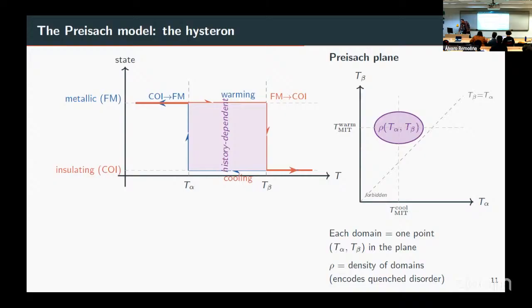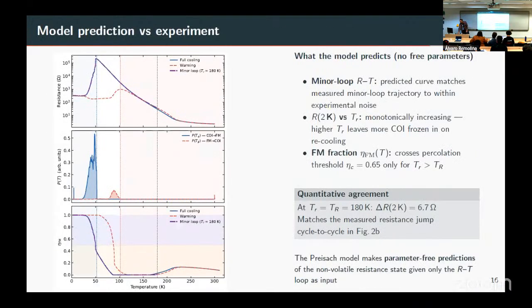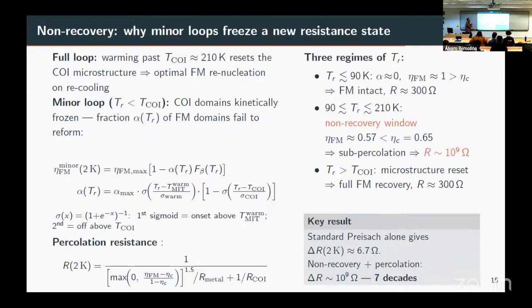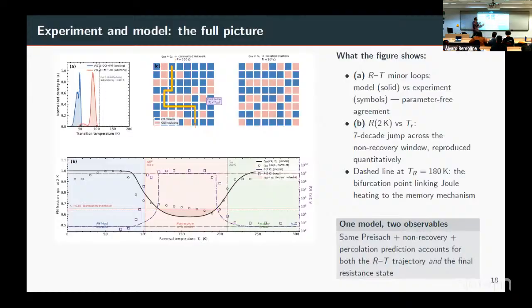And the other important parameter here, which I was too fast to explain, is this alpha, the ferromagnetic phase fraction. Typically, this ferromagnetic phase fraction doesn't depend on the history of the temperature. But here, I introduced a cutoff. It's basically putting into the model the fact that if you go to a certain temperature and then reverse, not all of the domains reverse back. That is the trick to reproduce these whole curves. So the fact that this curve follows the magnetization and this one follows the resistance uses only those two parameters.